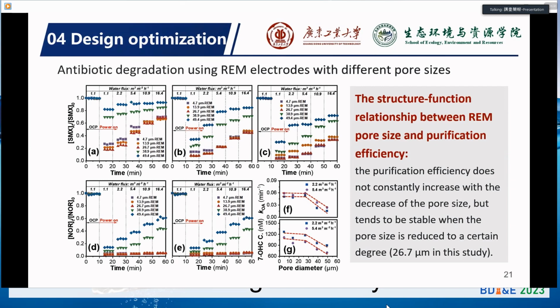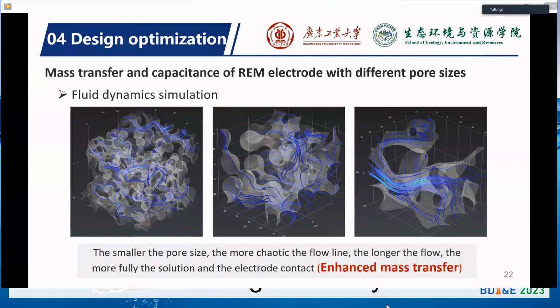A structure-function relationship has been observed between the REM pore size and the purification efficiency. We found the purification efficiency does not constantly increase with a decrease of the pore size, but tends to be stable when the pore size is reduced to a certain value, around 27 micrometers in this study. This seems inconsistent with our knowledge of the enhanced mass transfer and the capacitance of REM electrodes at a smaller pore size.